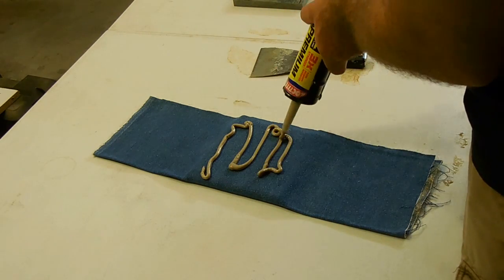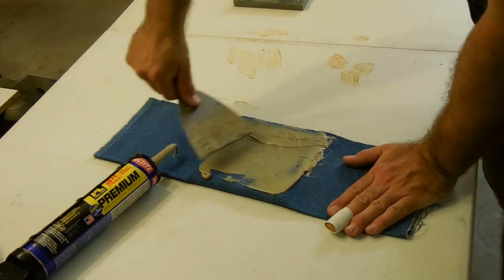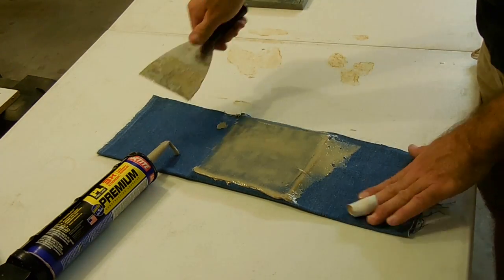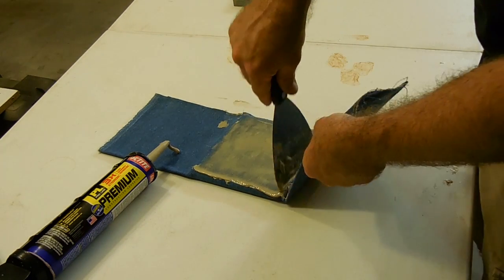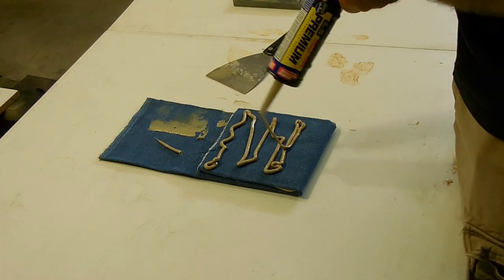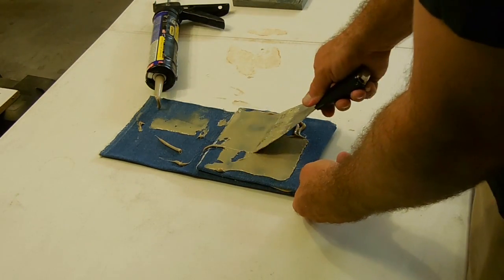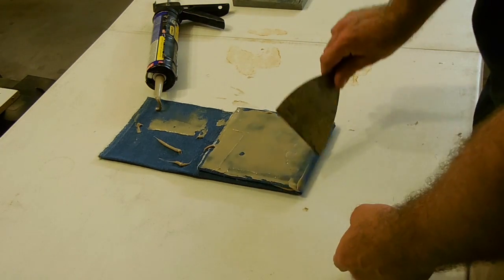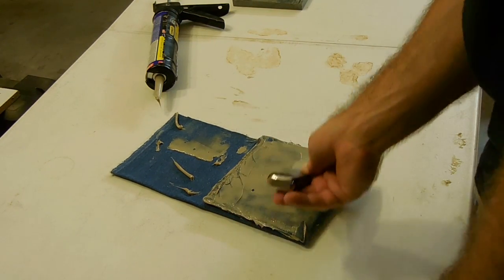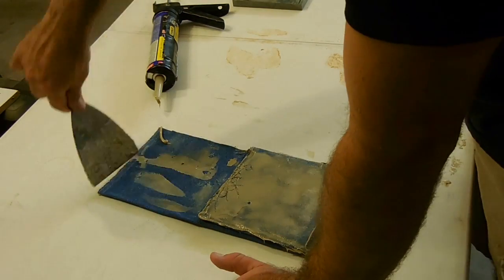In these tests, this simple plate design is capable of taking at least one round as long as it hits the tile. If subsequent rounds don't impact too close to the initial impact area, it can take more than one round. These plates, as long as they don't take a hit in the same spot or right on the edges, can take a couple hits and still keep on ticking.